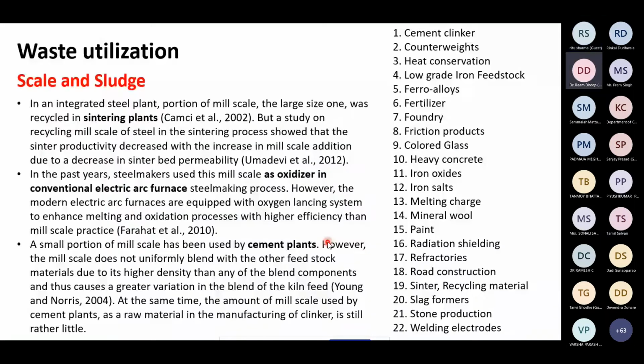Okay. Coming to waste utilization again. So now going to mill scale and mill sludge. In an integrated steel plant, a portion of the mill scale, the large size ones, was recycled in sintering plants. But a study of recycling mill scale of steel in the sintering process showed that the sinter productivity decreases with the increase in the mill scale addition due to the decrease in the sinter bed permeability.